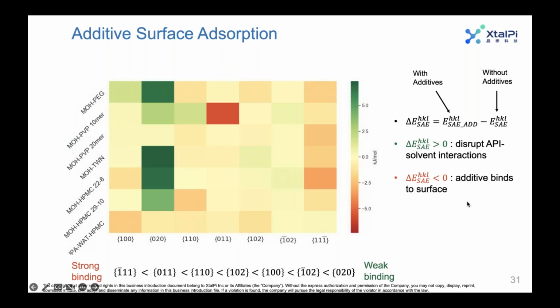And then for many of the faces, we saw that it was the effect of the additive binding to the surface. Now, we did notice that the polymers do modulate the growth rate of all the surfaces, but what we found is that for the fastest growing faces, slowing down the growth rate a little bit didn't have a profound effect on the morphology, because even though you've slowed the growth rate a little bit, proportionately, you didn't slow it down enough to make that face morphologically important. Rather, we saw that the polymers have the greatest effect on the faces that are already growing slowly, specifically the 100 face, the 020 face, and the 110 face.